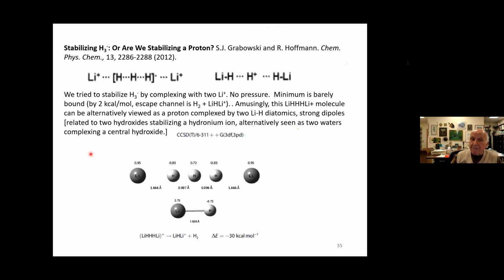We tried to stabilize H3 minus at 1 atmosphere. How would you stabilize something which is a saddle point? Well, obviously, since it's minus, you've got to attach some positive things to it. So we put a lithium at each end. You see it here. And in fact, this was bound, barely bound. The 2 lithium pluses and an H3 minus, but it's a model for what it could be in a solid state.